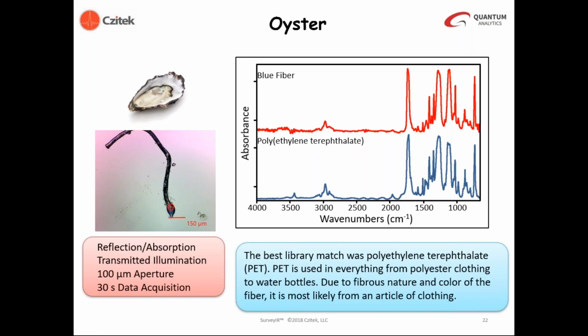With low E-glass slides, we're able to observe samples in transmitted or reflected light illumination, but they're very reflective to infrared radiation. So we record the spectrum by double pass reflection through the material. And we can actually see in this case where we analyzed this fiber. The fiber is only about 20 microns in diameter, but we flattened out a portion of the fiber to get an appropriate infrared path length, and that also increases the size. So in this case, we used a 100 micrometer aperture, and the red spectrum on the top was the result.